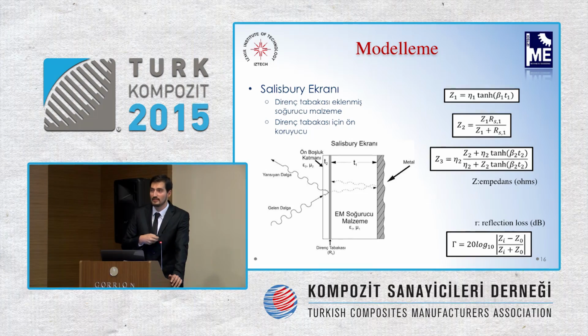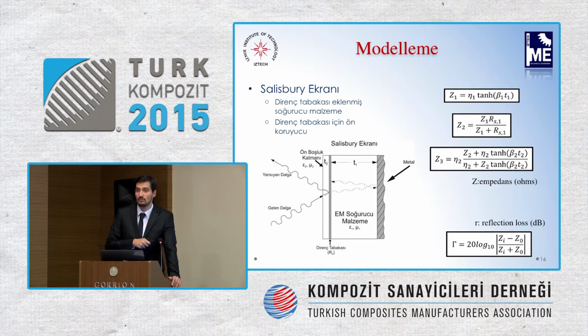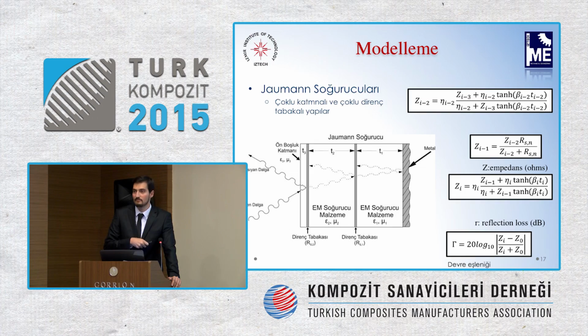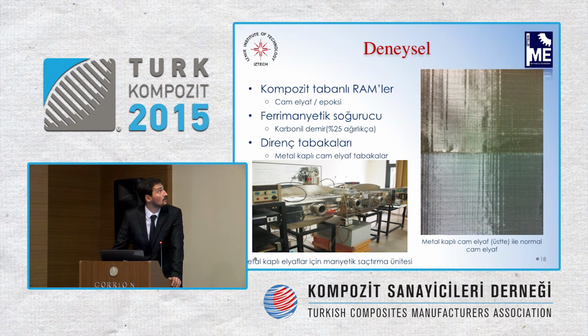Salisbury screen, there is a tiny modification here, because we have to get closer to reality. We have continuously reinforced composites, and on the outer part, we have an epoxy layer. It's not a full resistance, and epoxy has our filling material. Therefore, we have a air-gap layer instead of the resistance layer, and it is thick to a certain point. These are variables of the design, and we put them in the genetic algorithm. Jaumann absorber, the number of the resistive sheets increased here, and we used all of this in genetic algorithm optimization, and we have a air-gap layer.